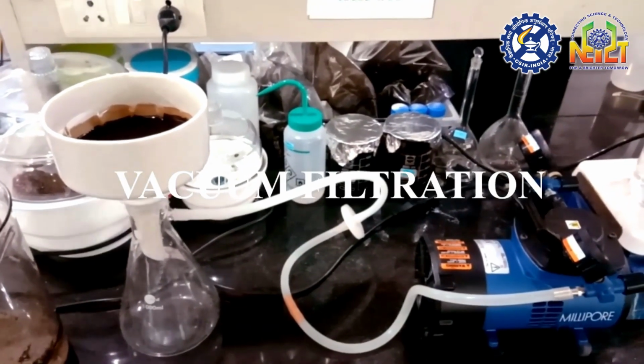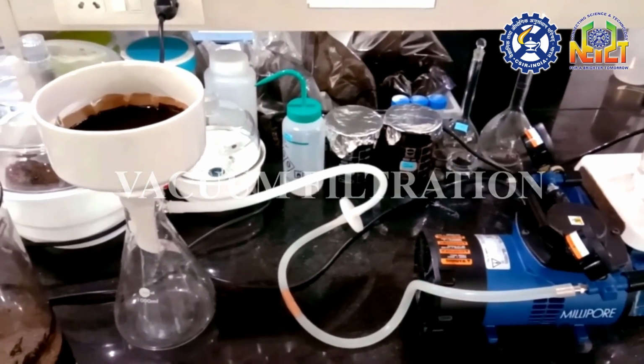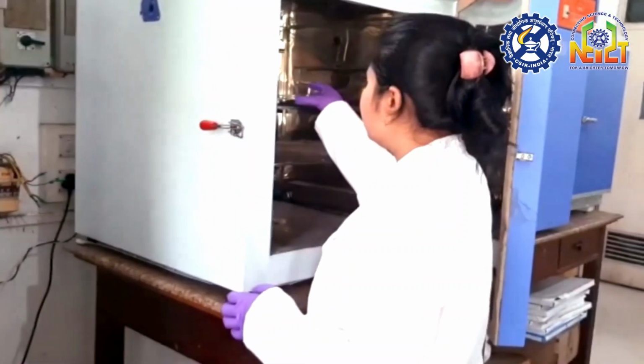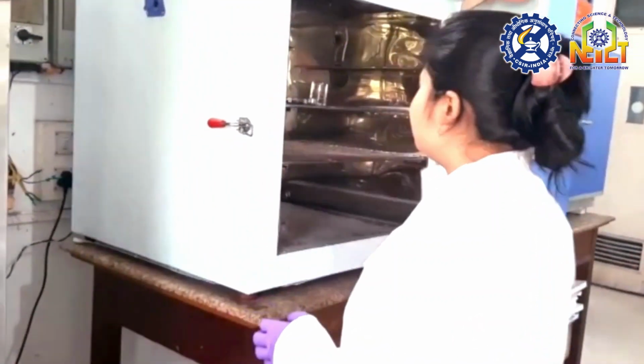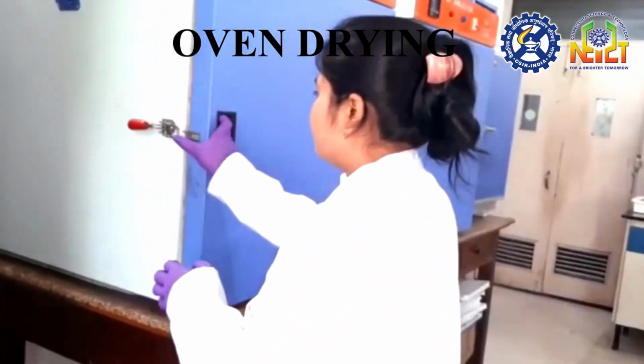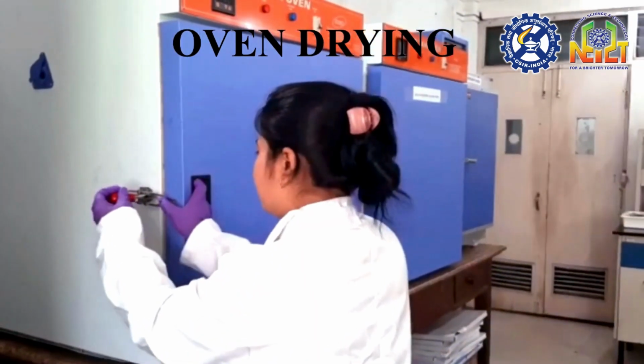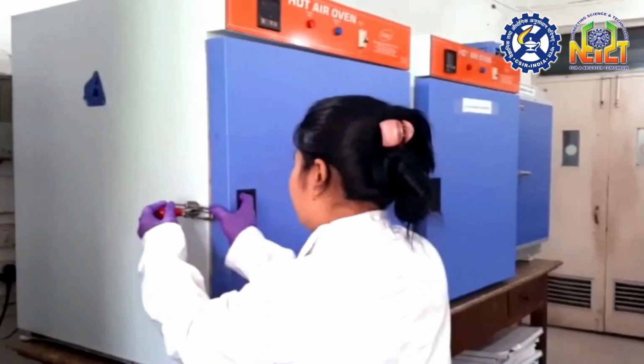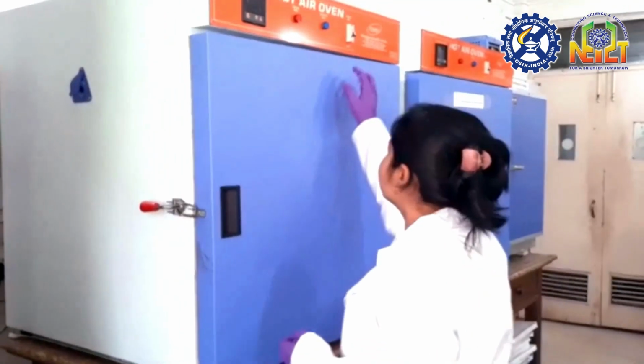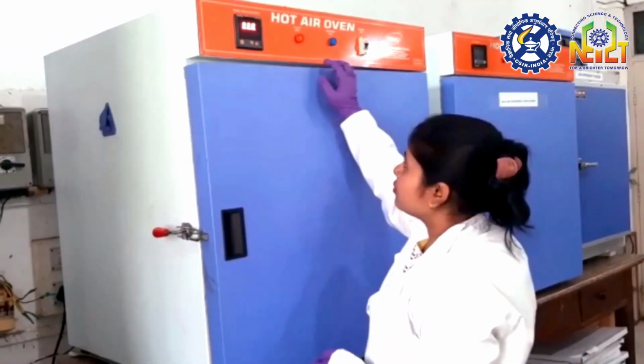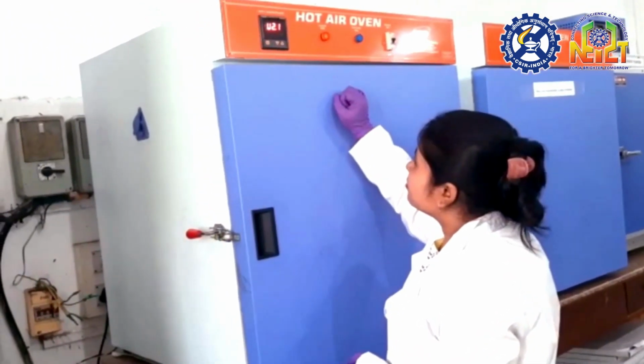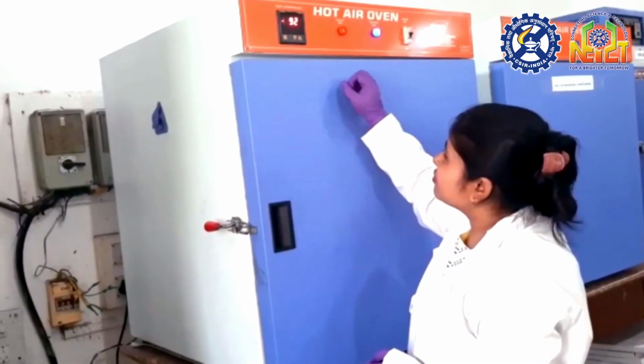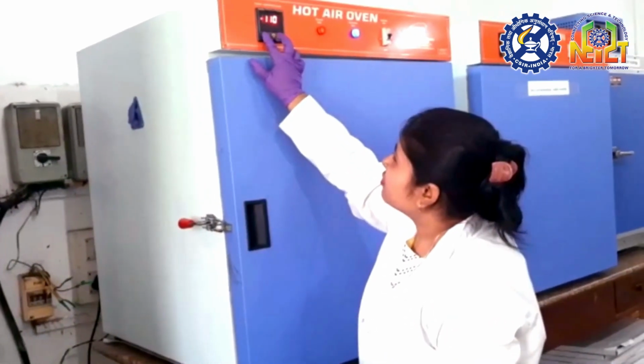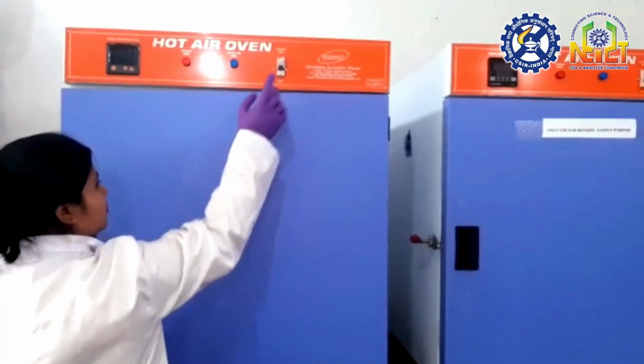Lastly, the synthesized product was cleaned with a 0.1 N acid solution, and then distilled water was added to get the solution neutral. The obtained products were dried in a hot air oven at 100 degrees Celsius and the required activated carbons were obtained.